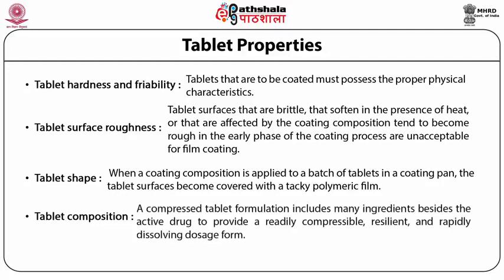The fourth parameter is tablet composition. A compressed tablet formulation includes many ingredients beside the active drug to provide a readily compressible and rapidly dissolving solid dosage form. The resulting surface properties of tablets depend on the chemical nature of the ingredients utilized in the formulation. For the coating to adhere to the tablet, the coating composition must wet the surface. Hydrophobic tablet surfaces are difficult to coat with aqueous-based coatings. The composition of the coating formulation can be adjusted through the addition of appropriate surfactants to reduce surface tension of the coating composition and improve coating adhesion.